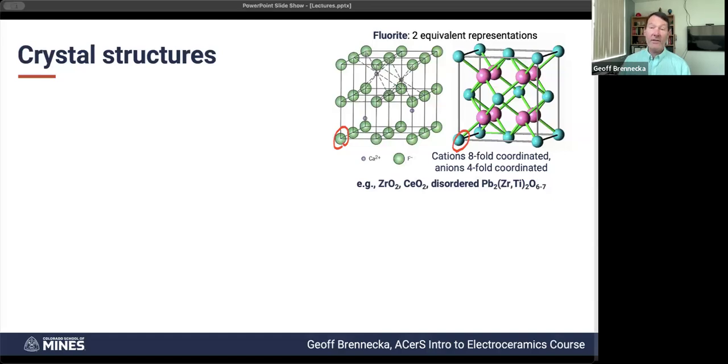The point that I want to make on this one is that if you look at the anion-centric version, so this one over here, you can see that there are 4 cations. If you can imagine that cube, there are 8 centers of these sort of subcubes within the structure, and half of those are filled with cations. Hopefully you can imagine that in your head.